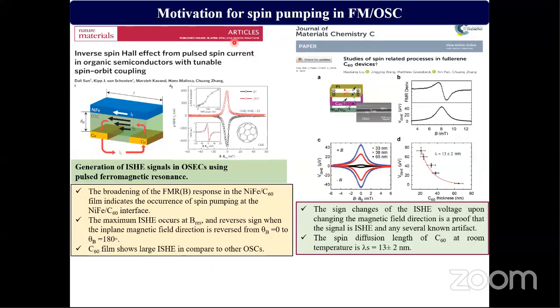There are few reports on spin pumping in ferromagnet organic semiconductor systems. Here they have taken NiFe as a ferromagnet and varied the organic semiconducting material, and they used pulsed ferromagnetic resonance to generate the ISHE signal. They observed that the C60 film shows a higher ISHE signal compared to the other organic semiconducting materials. The other paper is by Liu et al. They also took the NiFe C60 film and observed spin pumping. Here they took a platinum layer to detect the spin current.